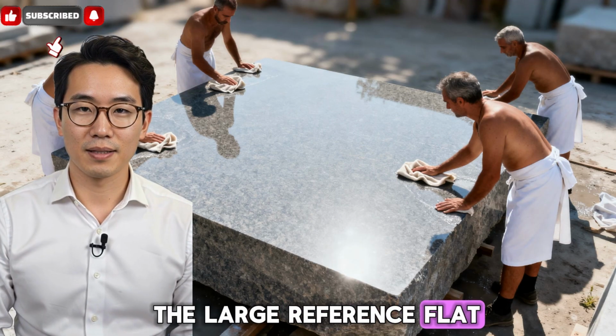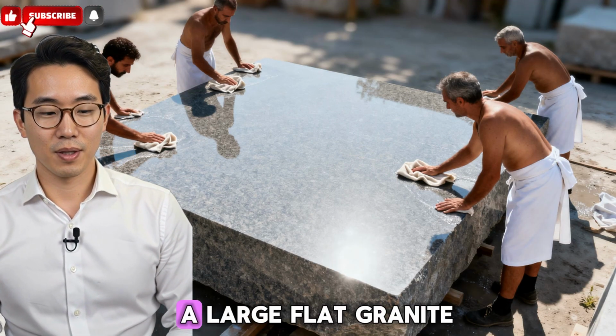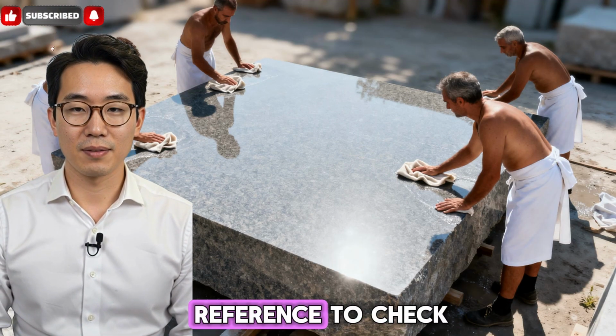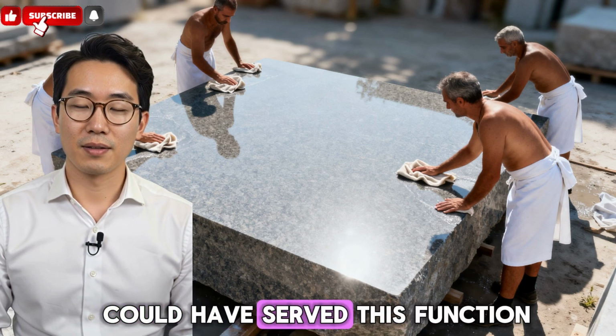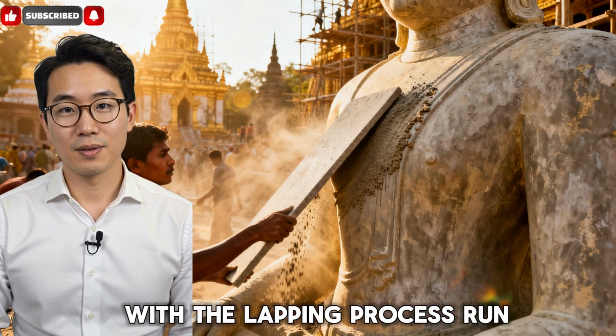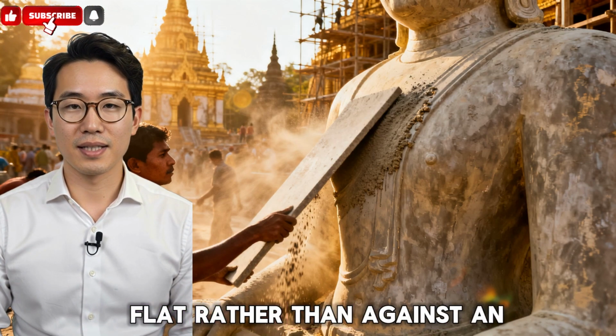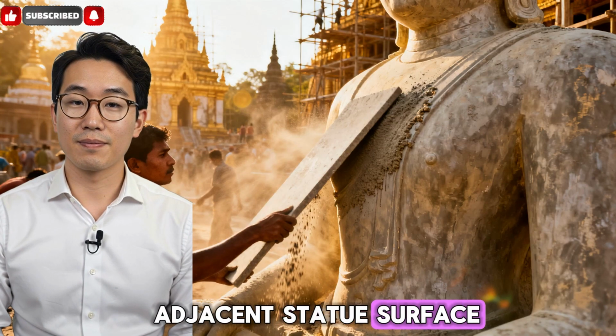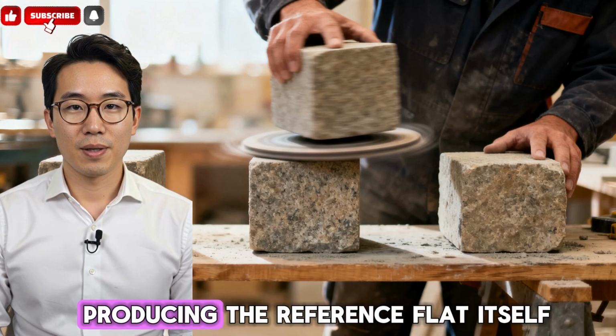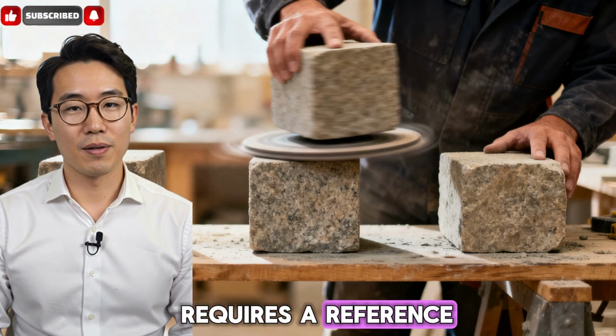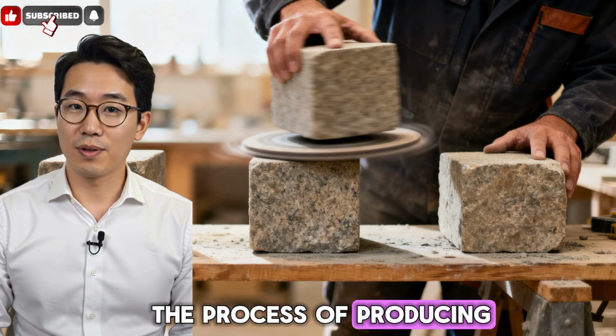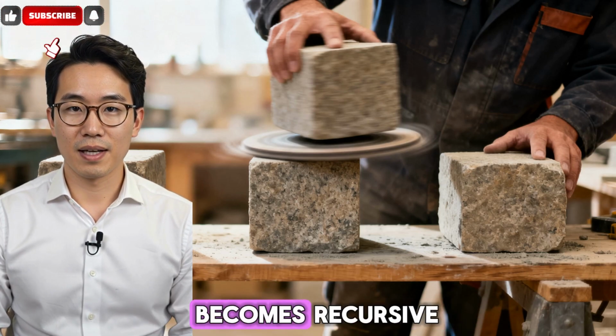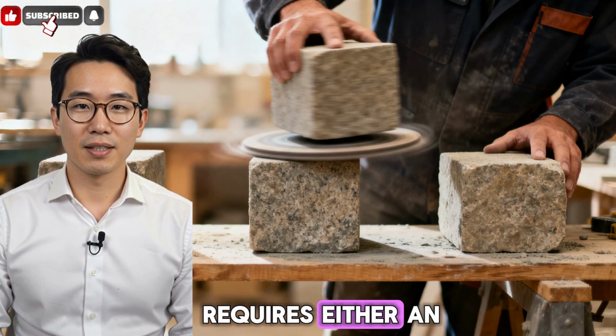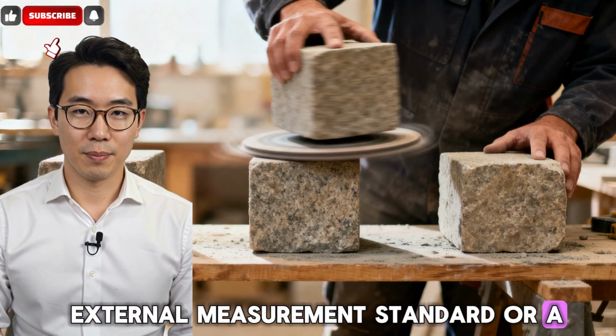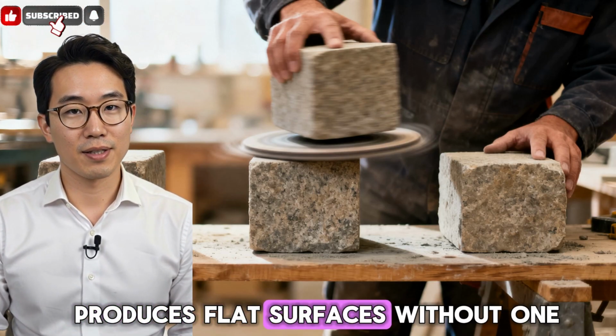The large reference flat approach is plausible in principle. A large flat granite slab used as a reference to check the statue surface could have served this function, with the lapping process run against the reference flat rather than against an adjacent statue surface. The practical limitation is that producing the reference flat itself requires a reference, and at some point the process of producing consistently flat surfaces becomes recursive in a way that requires either an external measurement standard or a mechanism that inherently produces flat surfaces without one.